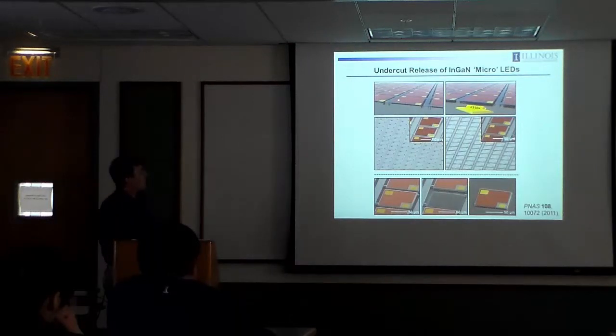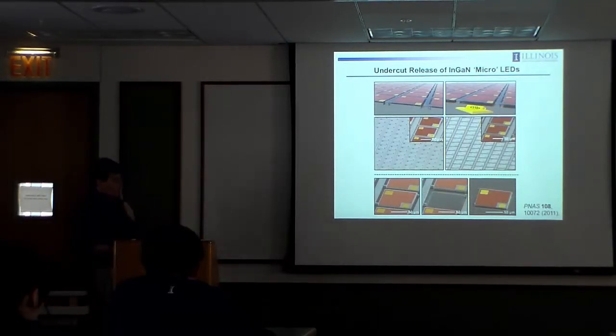And so if you orient your devices that you create in the InGaN material grown on this wafer in this fashion, such that you have anchor bars running along this direction and this direction, then when you etch down to delineate the lateral dimensions of the devices, you expose a little bit of the silicon, you immerse that in potassium hydroxide, and then you undercut just along this direction. And so the devices then can be configured with little anchor points at the corners, and those provide tethers to these bars such that when these devices are completely undercut etched, they're sitting in a freely suspended configuration and they're ready for printing. So here's one of these devices, little anchor bars, come in with a stamp, pluck that off, fracture the bars, and then you can print the devices down wherever you want.